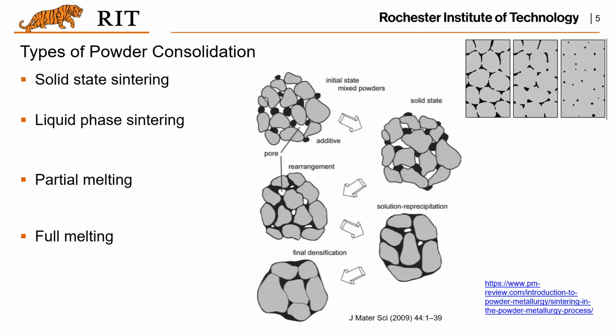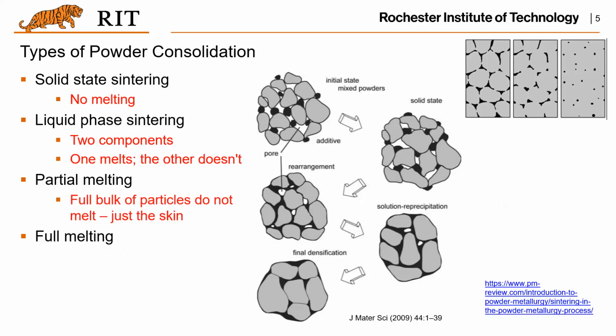And there are different powder consolidation methods, right? There is solid state sintering, where basically there's no melting at all. And also there are liquid phase ones, where basically of the two components, one melts and the other doesn't, or partially melts. So the full bulk of the particle does not melt, just the skin will melt. Or they are fully melting. So that will create a higher density, close to a full density process.